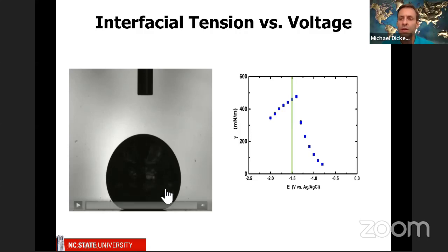So this is a droplet of the liquid metal. And again, it's sitting in sodium hydroxide, so there's no oxide layer on it. What you can't see is there's a little electrode poking into the bottom of this droplet, and it needs to be little so that we can see the shape of the drop. Based on the shape of the drop, we can get the surface tension. So right now the droplet has a very high surface tension because gravity is not able to squish it. Surface tension is bigger than gravity and it causes it to be a sphere.